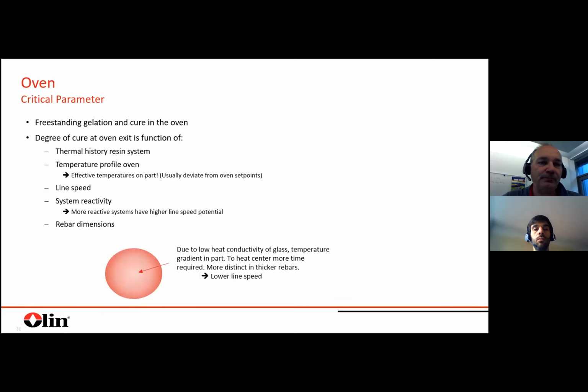So as mentioned, it's a freestanding gelation and cure in the oven. So regarding friction and interaction with a die, it's not a problem. It's really a function of how you achieve the degree of cure at the oven exit. And this degree of cure is a function of the thermal history of the resin. So mainly for sure in the oven, but also everything which is in front of it. The temperature profile in the oven.